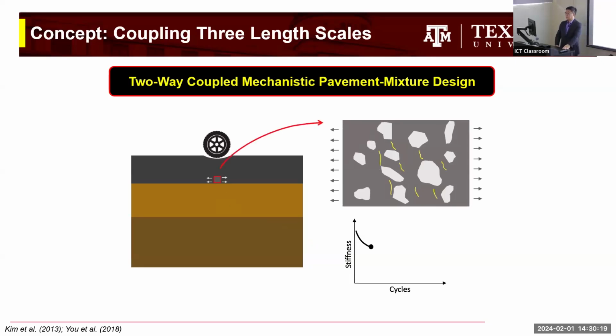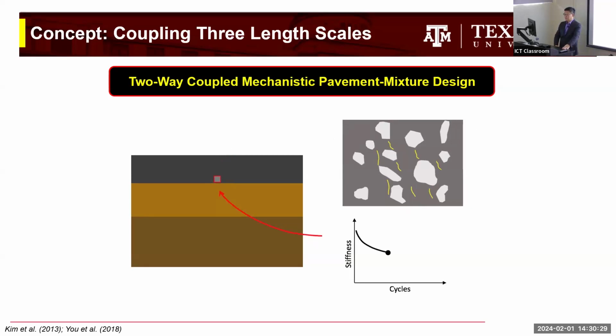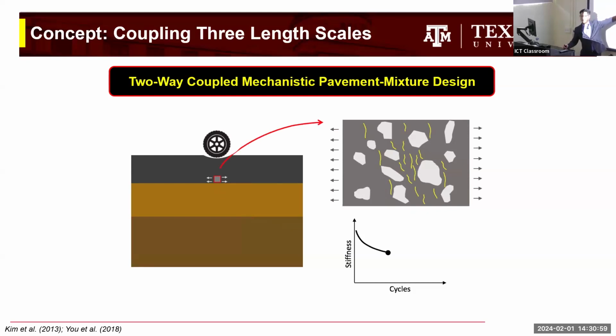And the next truck load comes in, and now we have more damage. Your stiffness drops again, and that reduced stiffness should be the input for the next time step. So in each time step, like a loading cycle, you need to account for this realistic evolution and change over and over. Large scale to small scale, like mixture and crack, and then small scale to large scale, it's looping. That's why we call it two-way coupling. And you notice the color right there is somewhat lighter gray, indicating a degraded location, degraded property. And it continues like this.